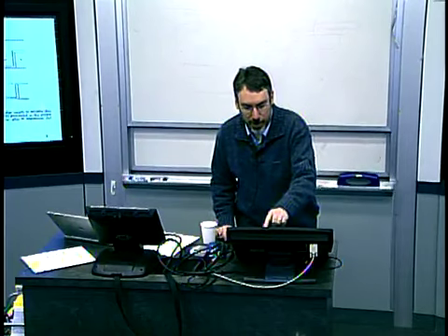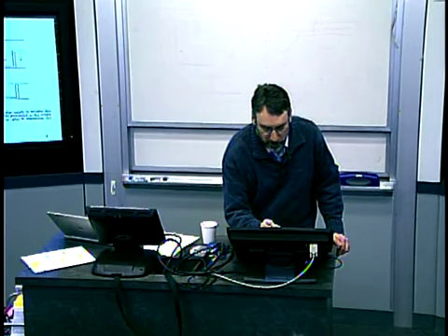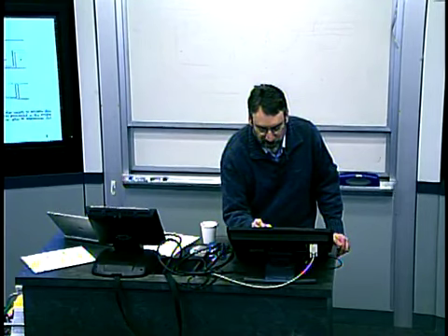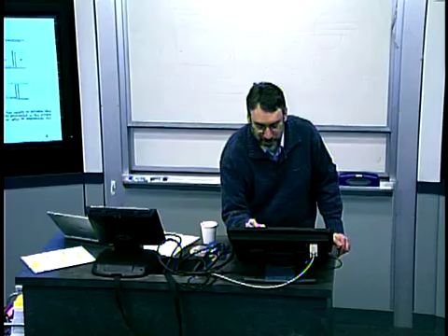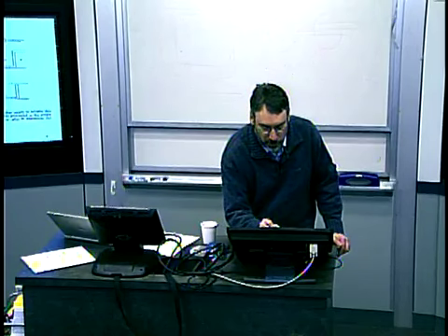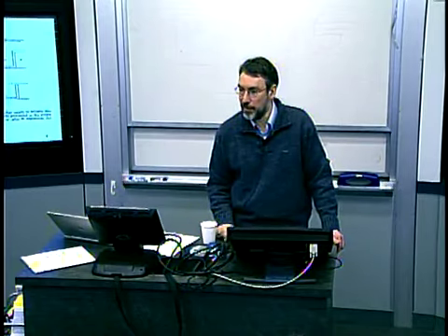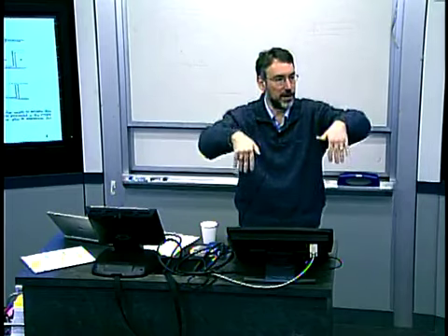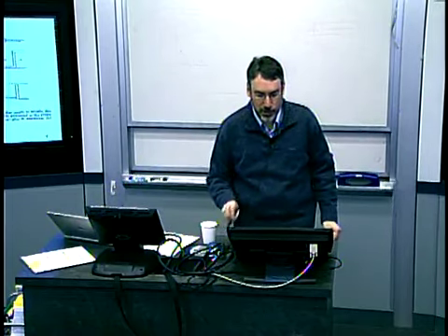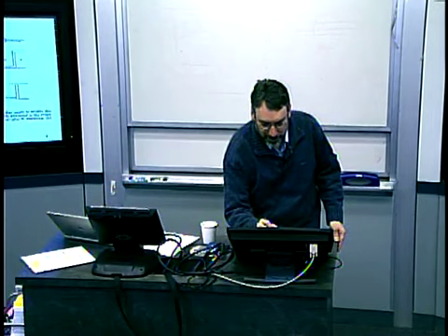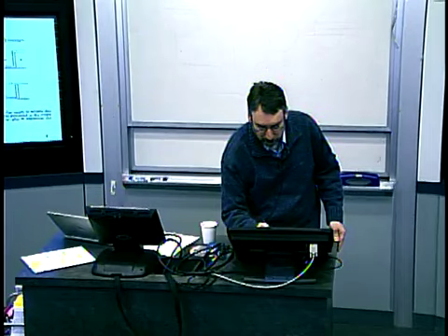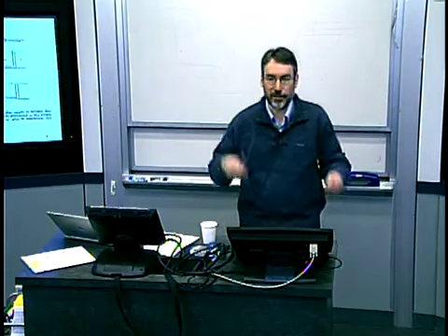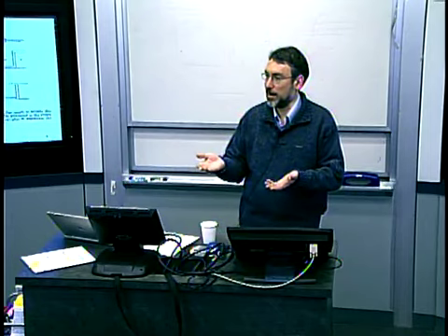And that has to do with surface roughness. So not only will these sorts of features, this topography, like that little dimple there, matter, but also if the surface of the deposited film is rough, and I do a uniform, sort of vertical, plasma etchback, that surface roughness may in truth be transmitted to the final surface of the plug.